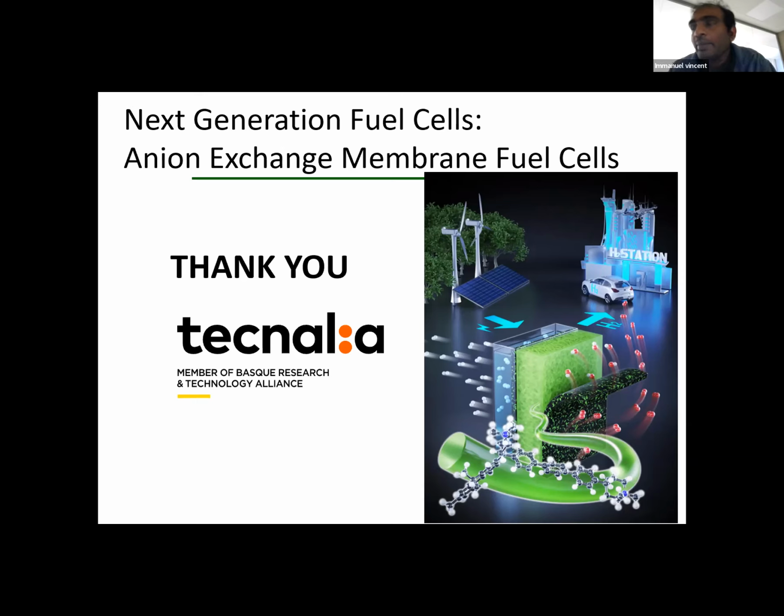Yes, Simon, I agree with you, because most of these membranes are much less stable in alkaline conditions due to nucleophilic attack and Hofmann elimination. But recently many papers reported this is mainly due to the ether components present in the polymer. So if we remove the ether component, then there is a possibility to improve the stability. But one problem: when we take out the ether, then there is low mechanical stability. But the chemical degradation such as this process can be avoided.